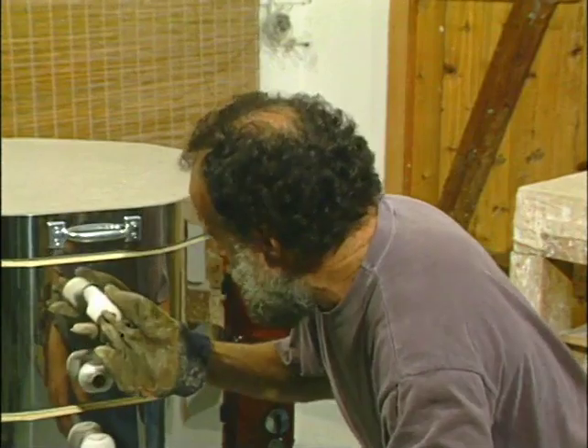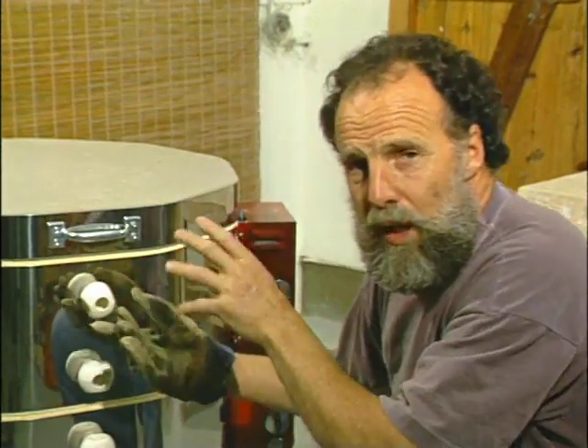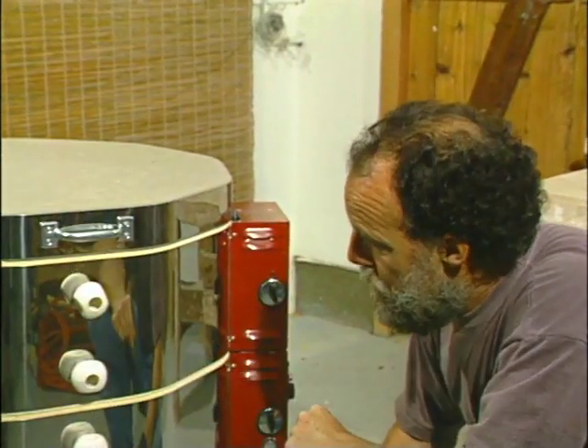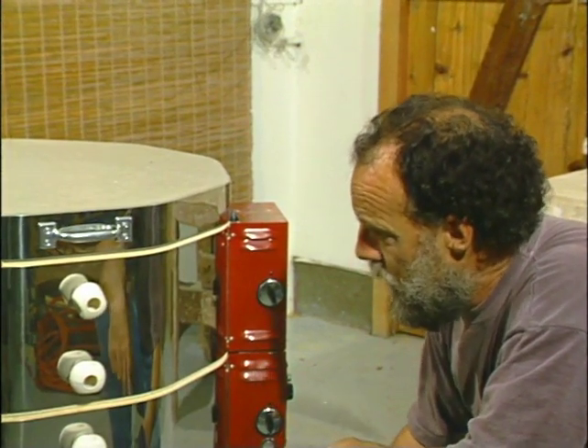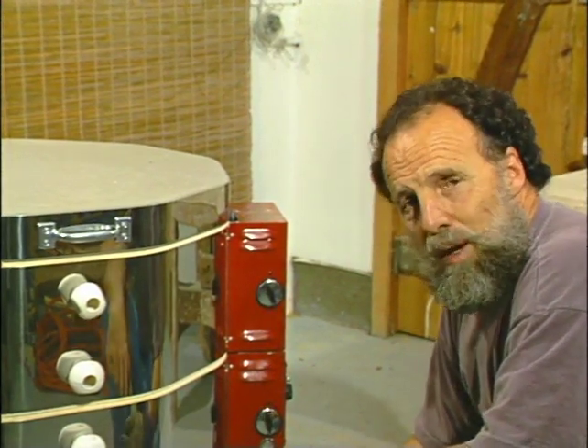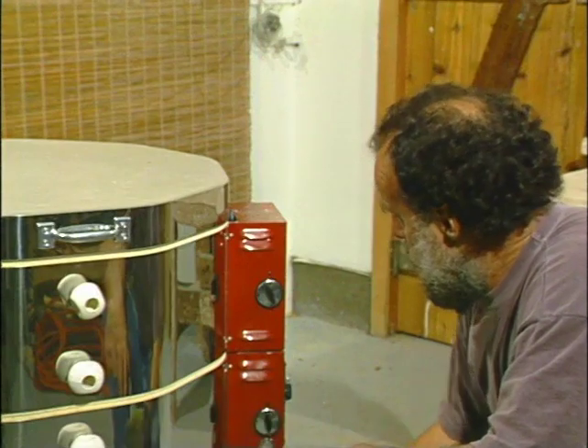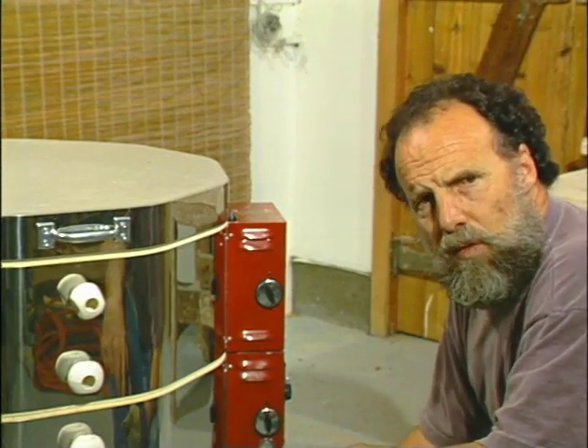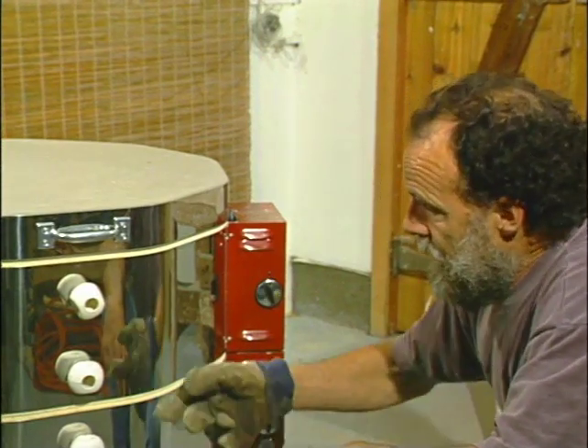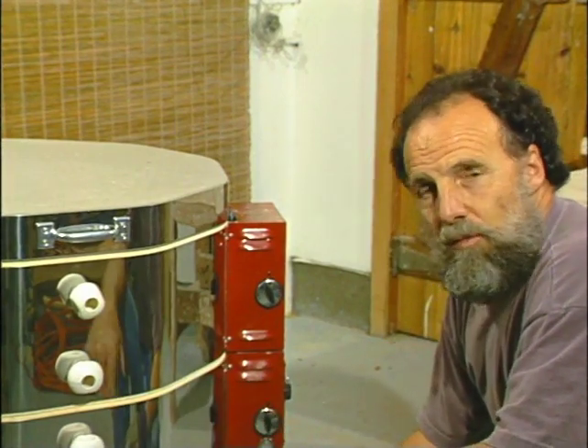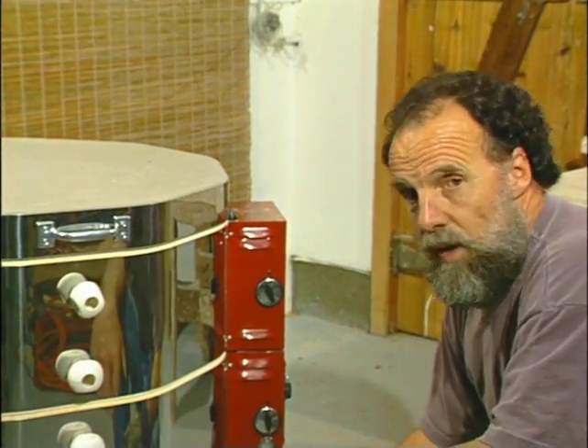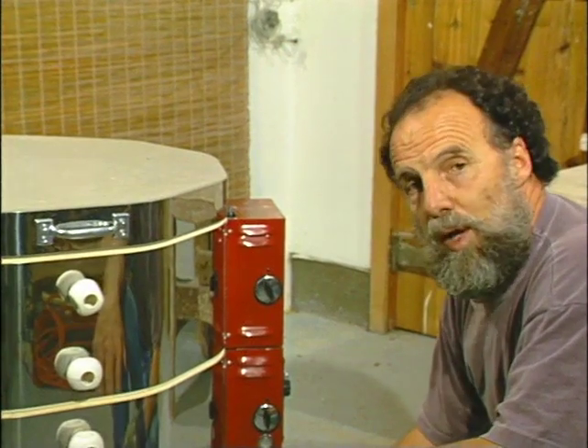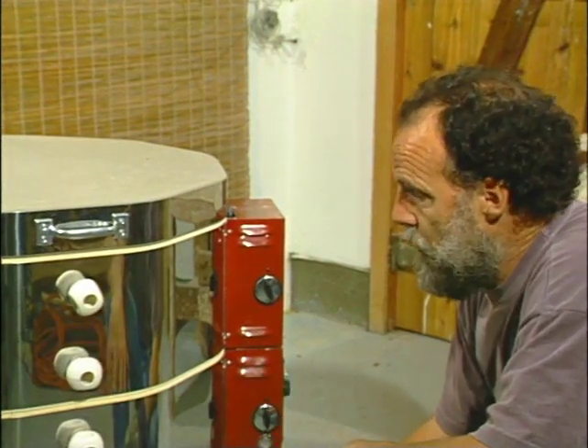Okay, I can just see a glowing red edge around the edges of the cones and the pots that I can see in through the spy hole. We've been firing for about 5 hours. We've had the elements on medium for the last couple of hours, and that means that we've got to about 500 or so in 5 hours. Well, that's a good moderate rate of progression, so we know we're on track so far.